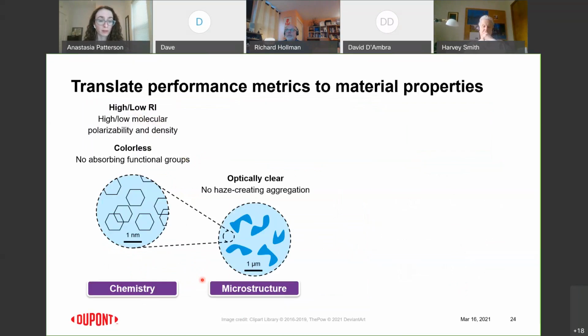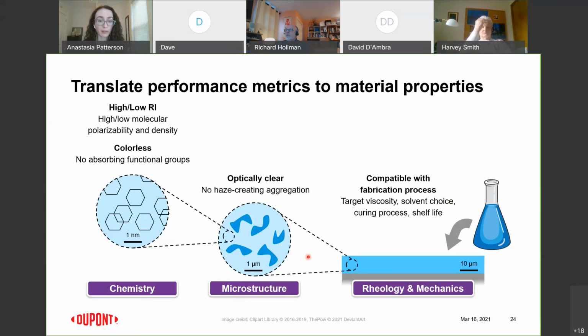We also need to keep in mind, taking a step out in length scale to the microstructural scale, that these films need to be optically clear. So they can't have any aggregation or haze creating elements in them that scatter light. And so this might bring to mind some sort of composite approaches that are often taken for increasing refractive index, but can create these kind of aggregation effects that are bad for the efficiency. And then taking one more step out to the rheology and the mechanics scale, any choices we make on this side have to be compatible with fabrication processes on the right side. So this could mean some sort of target viscosity, a solvent choice, a curing process, even shelf life.